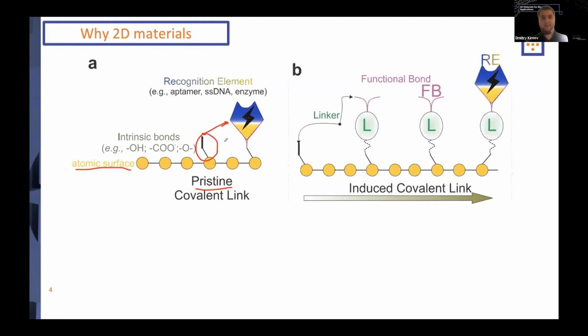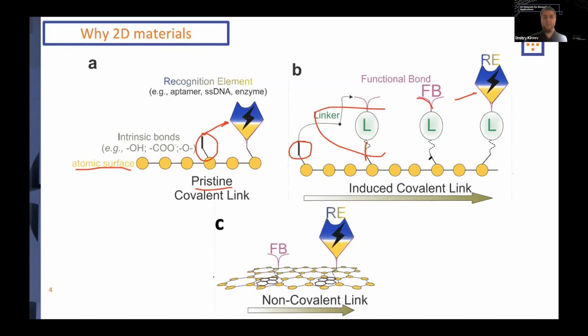It is rarely a reality, and you need to functionalize the bond. Between your intrinsic bond, you need to put a linker. It would react with your intrinsic bond, and on the other side, it would have a functional bond, and this functional bond would then react with the recognition element. This is the more common way of inducing a covalent link in your 2D biosensors. A third, and a really common approach specifically with graphene, is to make a non-covalent link. In this case, the most common molecule is an aromatic pyrene molecule that interacts with graphene non-covalently via pi-pi interaction. The interaction is pretty strong, so it stays on top, and you can bind the recognition element on top of graphene to really make a biosensor.